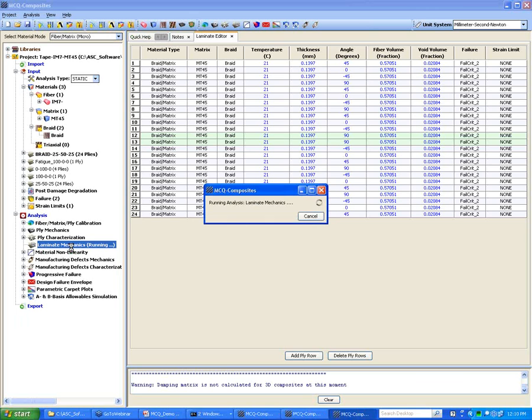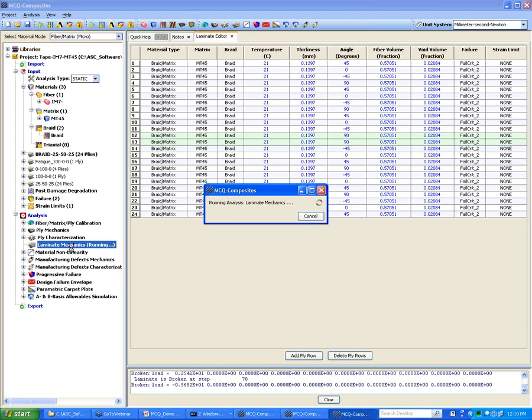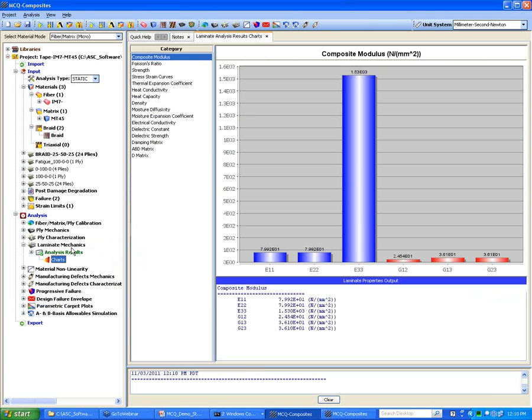At this point the software, without using any FE solver, uses an analytical approach combining progressive failure, micromechanics, and classical laminate theory to come up with equivalent ply properties for the braided or stitched material. The screen now shows the modulus: in-plane E1 and E2 are equal, and out-of-plane, because of the threads or fiber in the out-of-plane direction, is increased significantly.